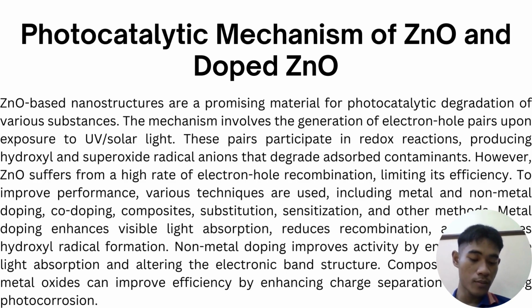To improve performance, various techniques are used, including metal and non-metal doping, co-doping, composites, substitution, sensitization, and other methods. Metal doping enhances visible light absorption, reduces recombination, and promotes hydroxyl radical formation. Non-metal doping improves activity by enhancing visible light absorption and altering the electronic structure. Composites with other metal oxides can improve efficiency by enhancing charge separation and reducing photocorrosion.